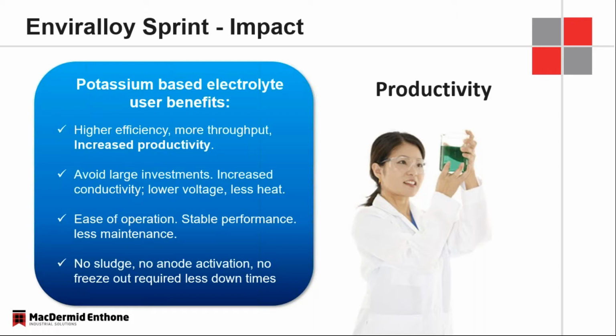So if you're an applicator, and just for round numbers, say it takes you one shift to do 10,000 pounds of fasteners, and if you're able to use the Enviralloy Sprint process, we've actually seen where in that same time frame, you're going to be doing approximately 12,000 to 13,000 pounds of fasteners. So we're talking about an increase of 20 to 30% in productivity in the same time frame, which, as we all know, is extremely beneficial. It helps to decrease the need for large investments like adding on plating lines or adding on extra plating tanks. The increase in conductivity really matters a lot in lower voltages, so there's less strain and requirement for cooling capacity.